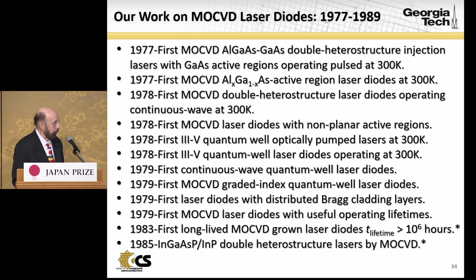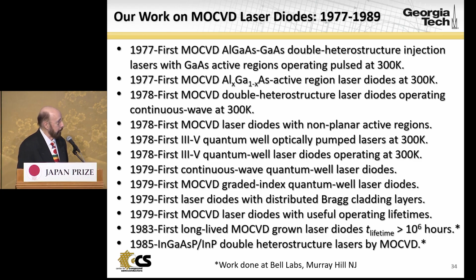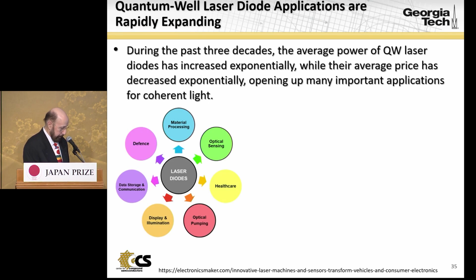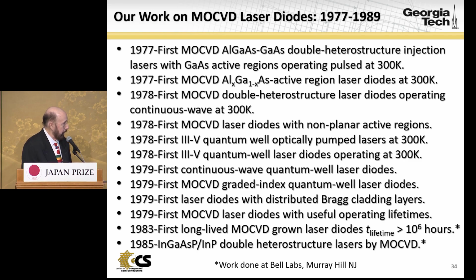In 1985, we reported the first 1.5 micron indium gallium arsenide phosphide double heterostructure lasers grown by atmospheric pressure MOCVD. So in this span of a few years, we established that MOCVD was a dominant technology for laser diodes, and in particular this event with long-lived laser diodes really set the stage, I think, for commitment to grow high reliability lasers by MOCVD.